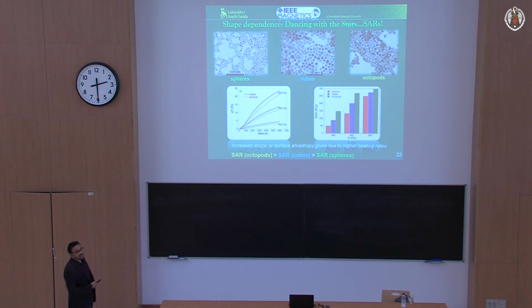So it's called dancing with the SARs, okay? So basically you go from spheres to cubes to octopods, and just look at this, there is a clear effect. If you increase the anisotropy, the shape or surface anisotropy or a combination, you get higher SARs for the same system. And I think we were one of the first groups that proposed this.